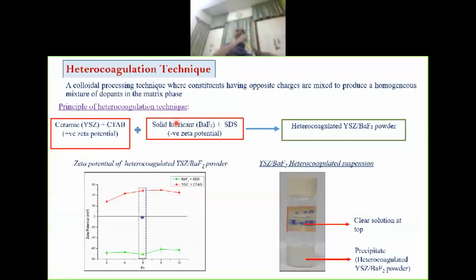Typical use of surfactants. Now, you mix, keep this mixture ready, positive, and this mixture ready. Add them up slowly. What will happen? Positives will get in touch with negatives and lose charge, come to zero. When they lose charge, they can agglomerate and hit the bottom of the container. No shaking, no breaking. You get a perfectly homogeneous, stable mixture that you have to dry out. So this is one procedure for powder mixing.